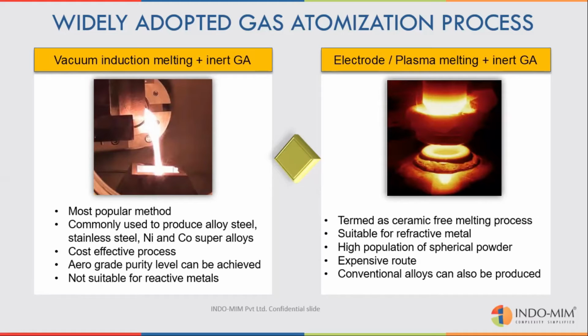Here, the electrodes, whatever the powder you want to make, that alloy itself becomes a bar stock, a feedstock of a wire or rod of high purity that will be used. It will be melted by either induction process or by the plasma and will be atomized. Since the ceramic crucible is available in the VIGA process, we call vacuum induction gas atomization VIGA process, there are possibilities of traces of some ceramic inclusions. To overcome such traces, this technique has evolved.